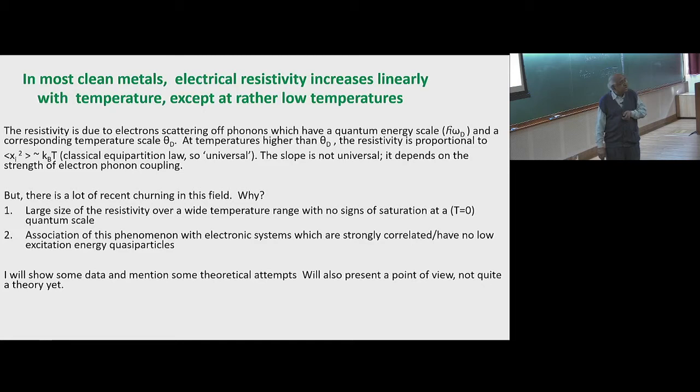Not only is it large over a wide range of temperatures, it exceeds some number which is embedded in our consciousness. It is called the Mott-Ioffe-Regel limit. It is the quantum limit of resistivity. Then another reason why people are very excited about this is that this phenomenon is associated with electronic systems in which the electrons seem to interact strongly with each other, and quite possibly there are no good quasi-particles.